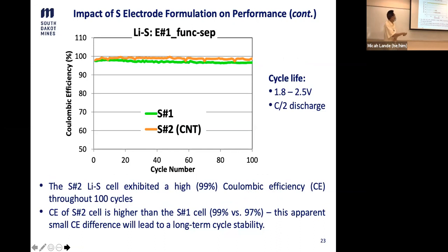Another figure of merit we look at is the coulombic efficiency. When we plot the coulombic efficiency versus cycle number, remember we like to have it as close to 100% as possible. For this S2 cell, you can see that it shows almost 99%, which is pretty close. For a battery, that is a good number. The second thing is that it's pretty stable, and it is a little bit higher than S1, let's say 2%. But this apparently small CE difference will lead to long-term stability, because if you cycle longer, with more cycles, that makes a difference, because S1 is less efficient and consumes more cell components.